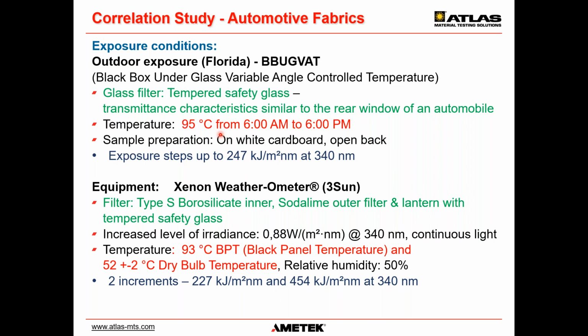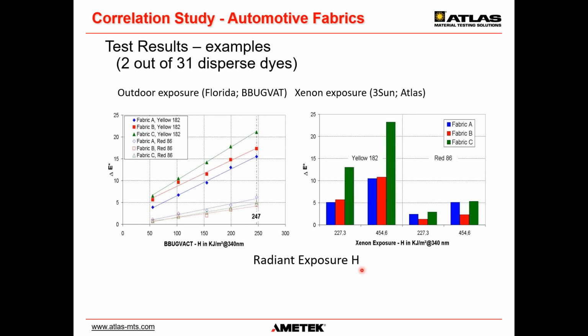So in black box under glass, outdoor exposure was done with controlled temperature, where the temperature was prevented from overheating and set to 95 degrees during the daytime, during the exposure time. And also an artificial setup, a xenon arc test setup, was chosen, which uses a high irradiance, about 3 times higher than the typical irradiance level we use in artificial weathering, and also at relatively high temperatures. So 1 exposure condition using the natural sun, and 1 using artificial solar radiation. The test has been done up to a specific radiant exposure with intermediate evaluations, of course.